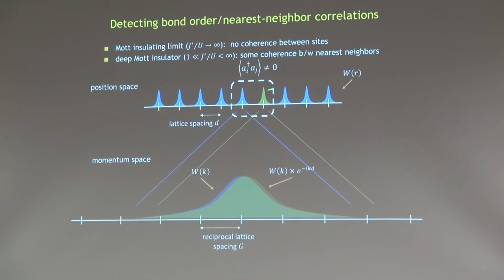But now, because the green site is translated from the blue site, the actual momentum space wave function for atoms coming out of the green site acquires a phase factor with respect to that of the blue site. That's simply what translation in position space does for you. So now if there is some coherence from one site to the next, these 2 wave functions will interfere and we'll see a modulation which reflects that interference. In other words, we will be able to see the signatures of 2-slit interference in the overall distribution of the expanded gas, so long as there's some coherence between 2 neighboring slits.